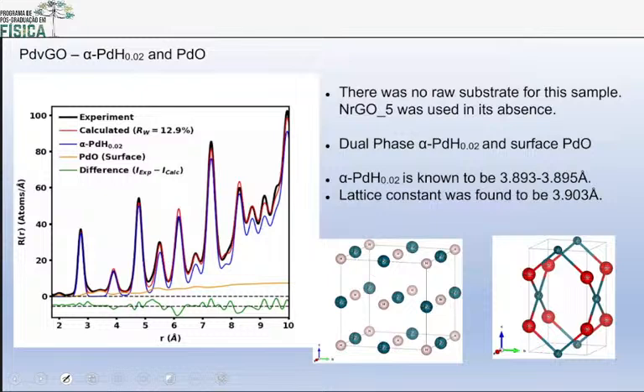Last one. Now this is important: my group right now is in the basement, working, and we're solving tons of nanoparticles for catalysis, for fuel cells. Here's an example: a chemist gave us samples of palladium, and it turned out it was palladium oxide and palladium hydride. The samples weren't what they thought they were. We did X-ray diffraction and figured out that we had 2 different phases. It completely explains why the physical or chemical properties of the nanoparticles weren't like pure palladium.